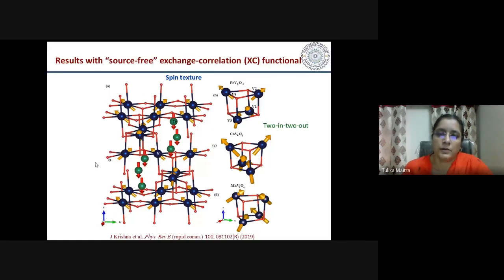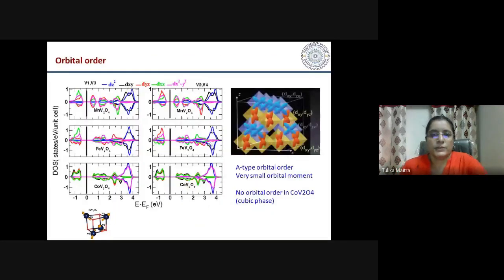Okay, so we could therefore explain or describe the non-collinear magnetic state using this source-free exchange correlation functional in the density functional theory. Both the magnetic moments as well as the canted magnetic state could be described by using this new exchange correlation functional. Further, we also calculated the orbital order by looking at the orbital occupation of the different orbitals.